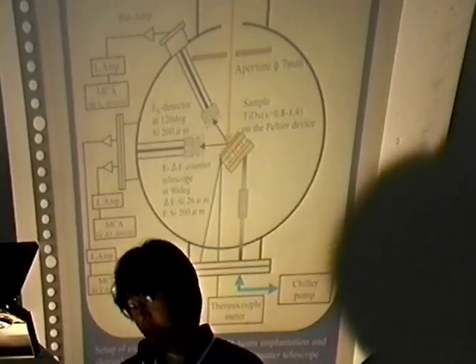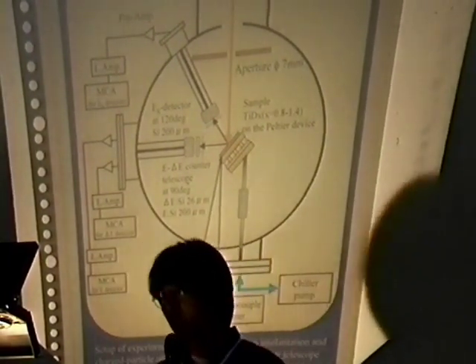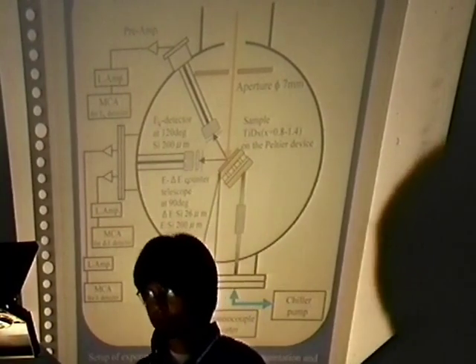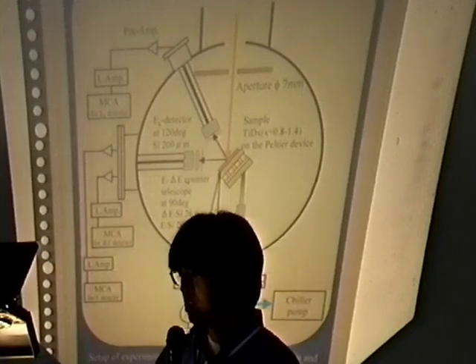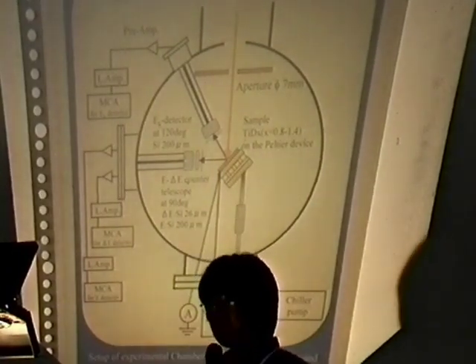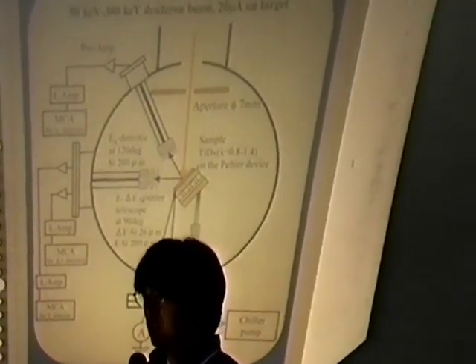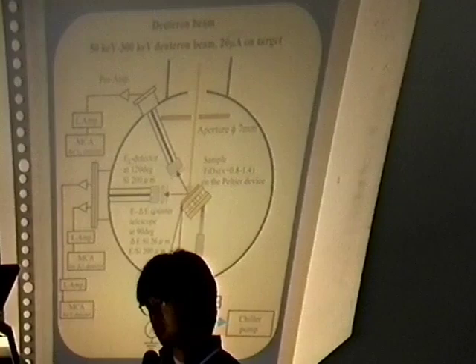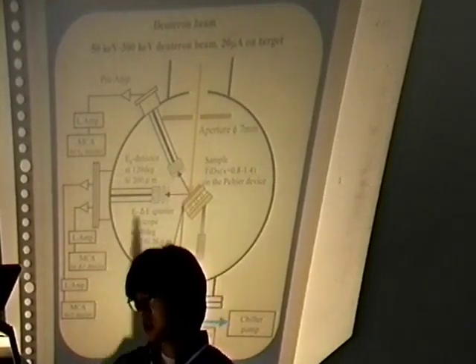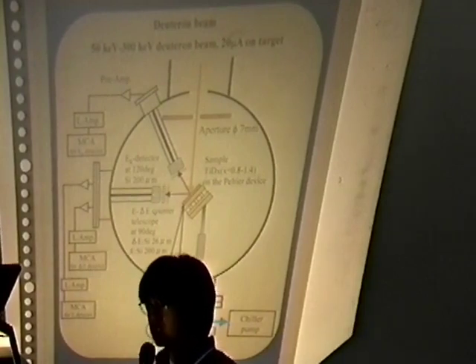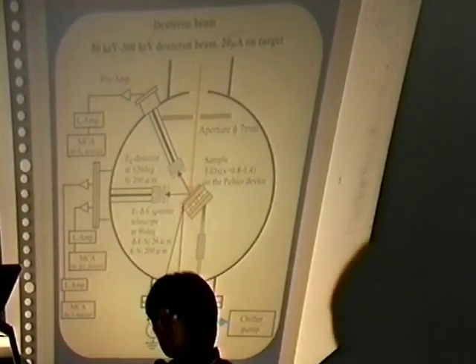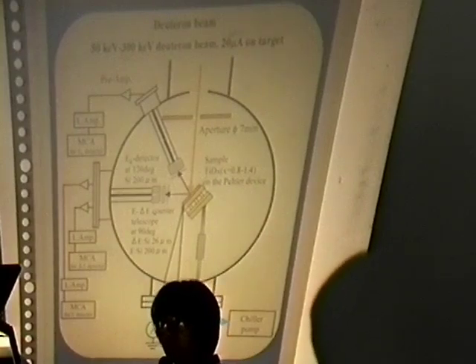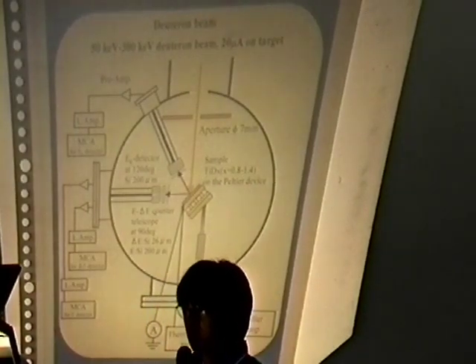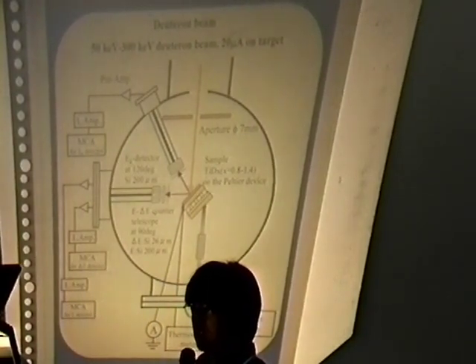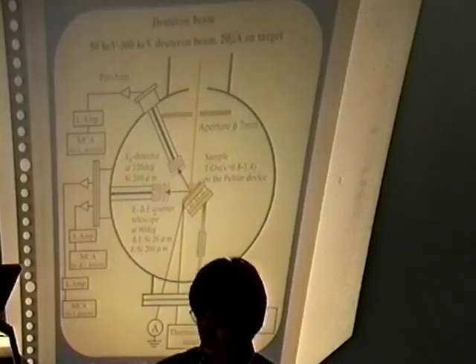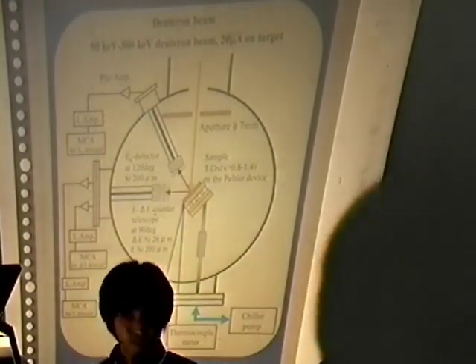This figure shows the setup of experimental chamber for deuteron beam implantation. Conventional SSBD were set here. This detector were used for the total energy measurement of the charged particles. And the E and the delta E counter telescope were set here. The sample was set on this cooling device. The beam energy was changed from 50 keV to 300 keV, and the beam current was about 20 microampere on target. And we call this detector E_d detector.